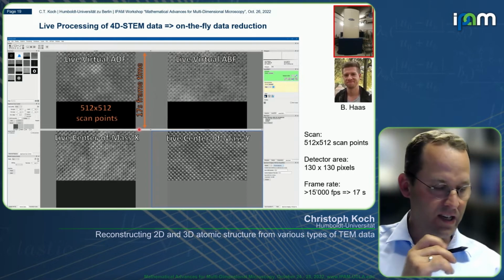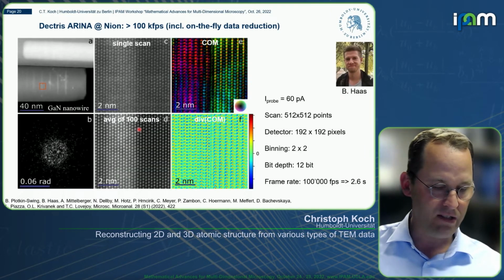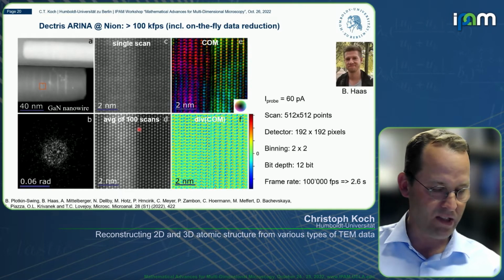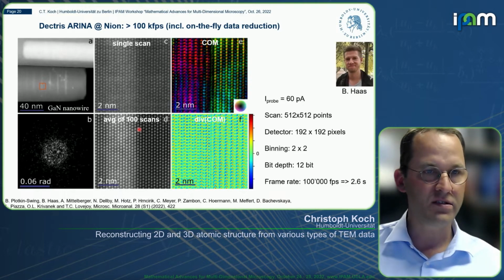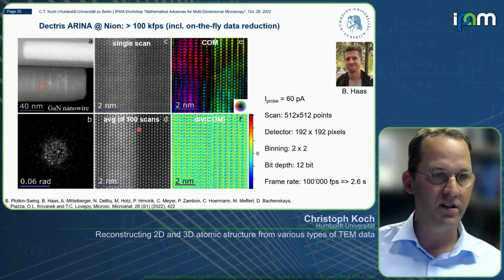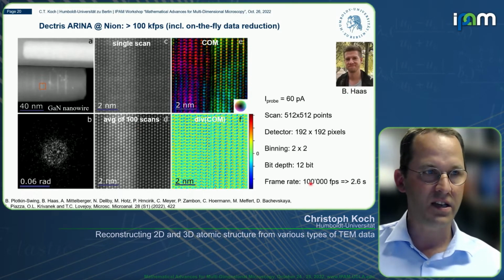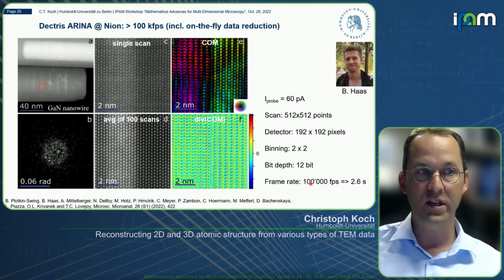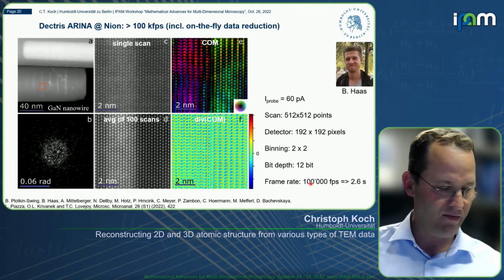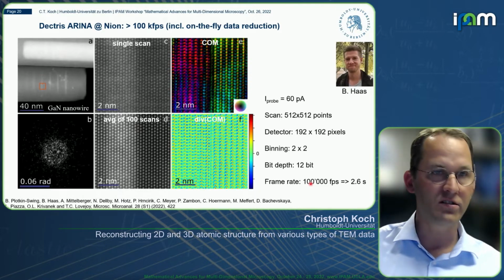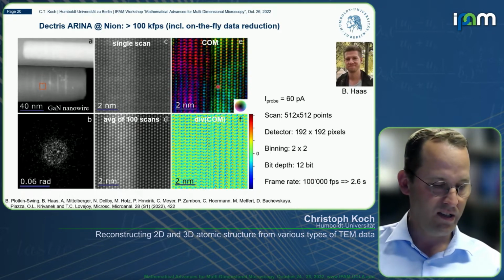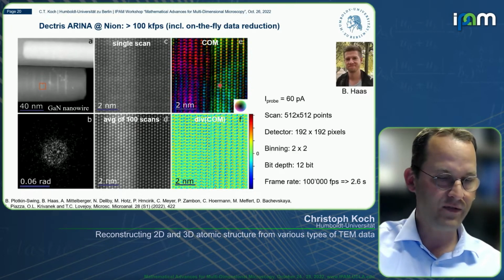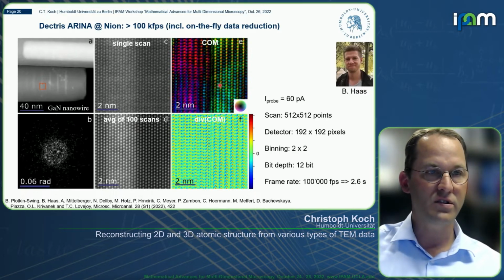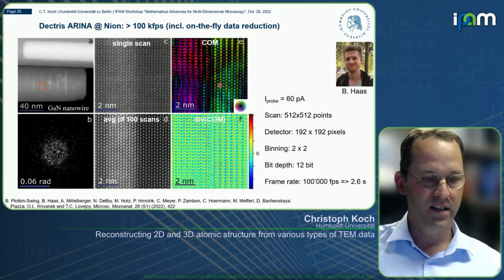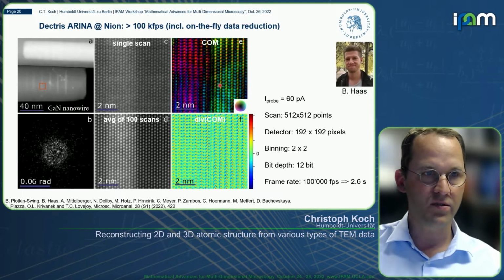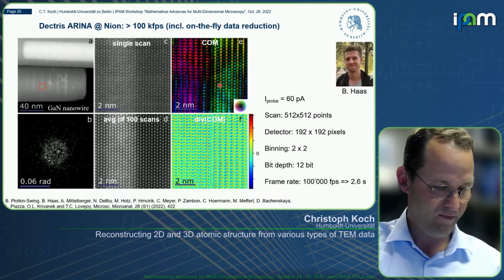So here Dectris also makes a faster detector that Benedict got to test at Nion. It's not installed on our microscope, but this now even runs up to more than 100,000 frames per second. So that means what took 17 seconds on our detector only now takes 2 seconds. And now you can really average also over multiple exposures, because it goes so fast. And you can then get the same kind of information, also the same kind of online data processing with much faster acquisition, which reduces, of course, distortions in your images, because you're not scanning over a moving target, but your target during the exposure is more likely to be stationary.